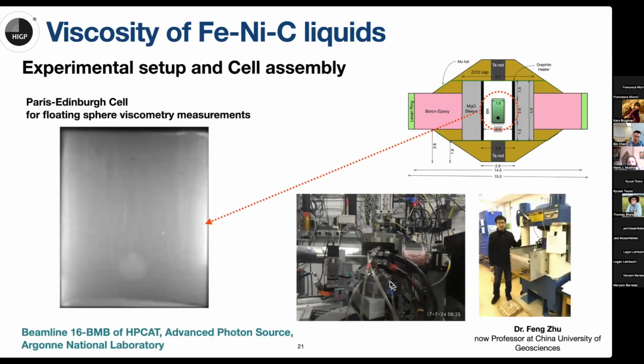We further performed our experiment in this same beamline, but we used the high-speed camera and viscometry to do this viscometry measurement. We placed a sapphire, Al2O3, the aluminum oxide sphere, in the iron nickel carbon mixture. After the sample is molten, this sphere would float to the top of the sample chamber because the density of this sphere is lighter than the iron nickel carbon liquid at high P-T conditions.